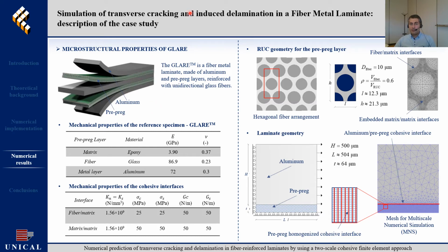Here, the elastic properties of the microconstituent are shown, as well as the inelastic parameters of the embedded cohesive interfaces used to simulate fiber matrix debonding and matrix cracking. The considered microstructure for the prepreg layer is made of 60% fibers with diameter of 10 microns and distributed in a regular hexagonal arrangement. Such a microstructure can be generated by the repetition of this rectangular unit cell.